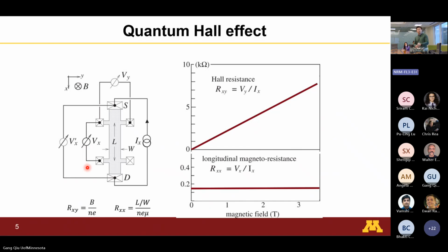Right? So the Drude model tells us that if you measure the Hall conductivity, because of the Lorentz force, you will see a linear Hall resistance as a function of external magnetic field. Basically, you apply a field perpendicular to the current direction, you will see a Hall voltage, right? And the longitudinal resistance is basically field independent for first order, okay?